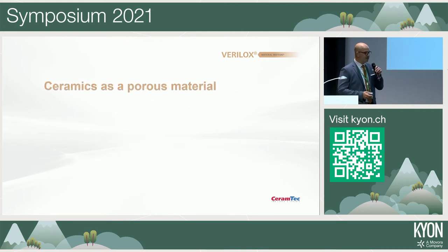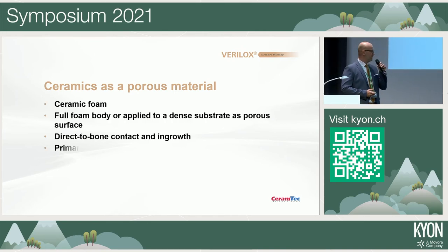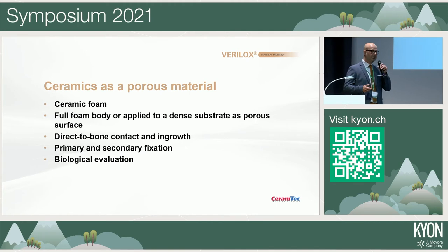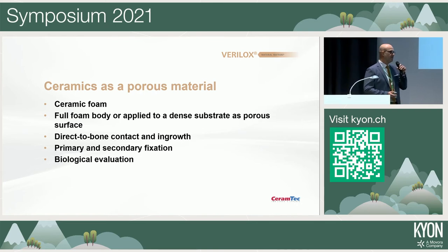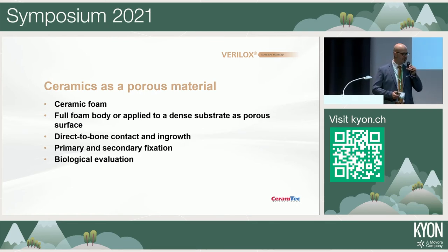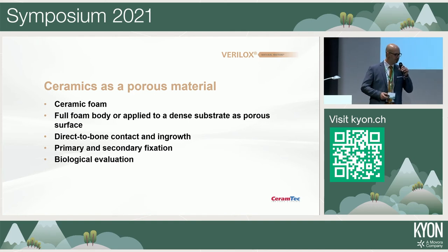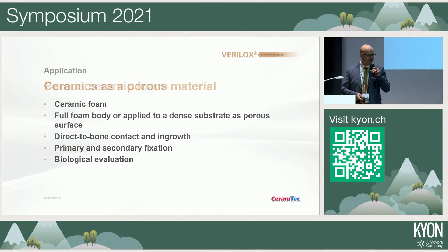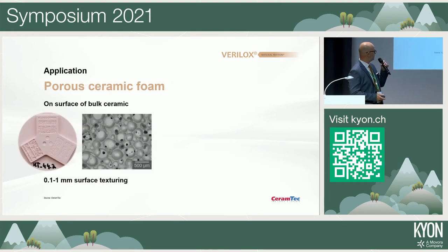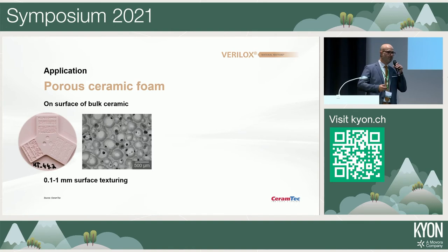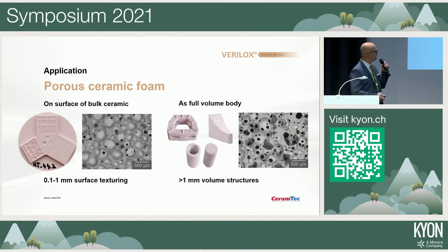Let's come to the next topic. What if I use ceramics as a porous material? Once again, we can do it as a foam. We can apply the foam to a bulk material as a kind of coating. And of course, these kind of porous structures are well suited for a direct contact to bone, for ingrowth of bone cells, and I want to show you the biological evaluation of that later. As I said before, we can do it on top of a surface. Then you simply have a layer of pores on top of a bulk material. And the second possibility is to use the foam itself to make geometries from that, like the examples here. We can do wedges, we can do cages. And the important thing is that the...